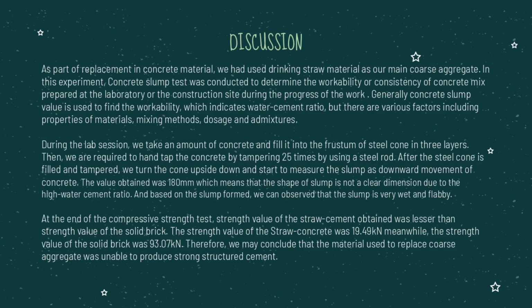At the end of the compressive strength test, the strength value of the straw cement obtained was lesser than the strength value of the solid brick. The strength value of straw concrete was 19.49 kN. Meanwhile, the strength value of the solid brick was 93.07 kN. Therefore, we may conclude that the material used to replace coarse aggregate was unable to produce strong structured cement.